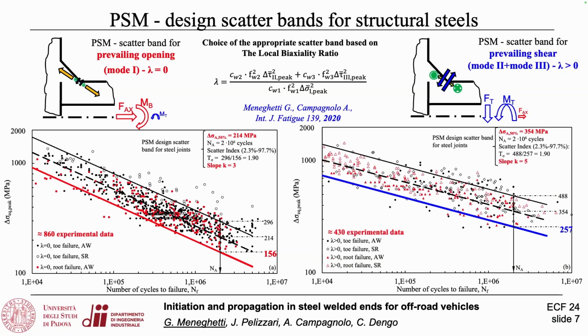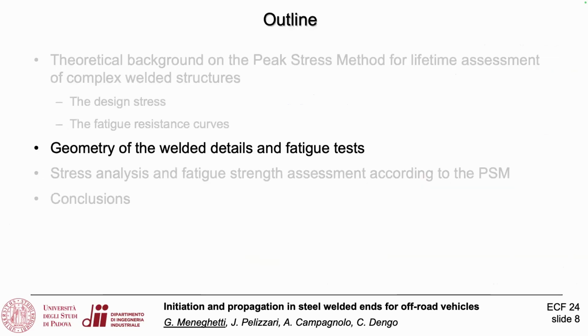As soon as you have lambda greater than 0, so as soon as you have shear modes in the strain energy density, you have to shift to a flatter slope of 5, and this is the design curve we found by fitting experimental data. So now the method is very quickly set up. We have the design stress and we have the resistance curves based on the values of lambda.